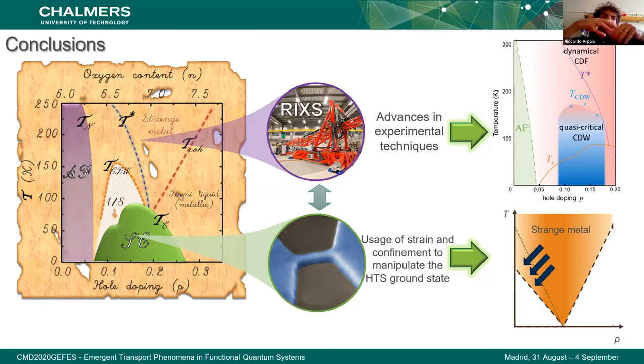So at high temperature, we have this sea of very small waves with very short correlation. And then when decreasing the temperature, at some point some of these very small islands start coagulating, giving rise to a charge order that is longer range, which is the one described by the charge density wave. Is the periodicity exactly the same? The periodicity, yes, is very similar because the Q vector associated to charge density fluctuations and charge density wave is basically the same.